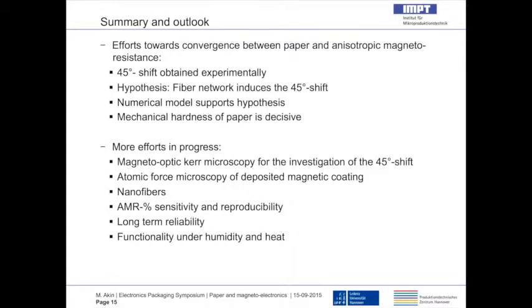In summary, what I showed you today are the efforts we have made towards convergence between paper and anisotropic magnetoresistance. What we have obtained experimentally is a shift of 45 degrees between the theoretical, well-known transfer characteristic on a smooth surface and on the paper surface. The hypothesis we have put forward is that the fiber network is the one that induces the 45-degree angle shift, because we were able to obtain the shift with two different measurement techniques. We have obtained the shift also on two different materials having the same surface properties. We were able to back up this hypothesis with a numerical model, and we showed you some efforts into optimizing these systems. The main conclusion we have drawn from these optimization efforts is that the mechanical hardness of the fibers is the most decisive factor for the magnetic properties of the coating.